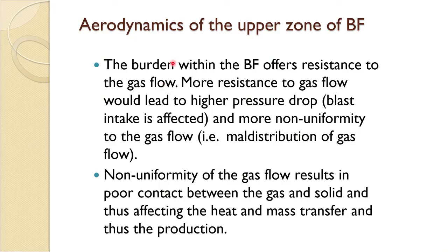It will just go without much resistance to the top, but if you put some material, naturally that material will offer resistance to the gas flow, and gas would always like to pass through the least resistance path. When you put granular material especially, it will form some voids, so gas will try to pass through the least resistance path, that is through those voids. More resistance to gas flow would lead to higher pressure drop. If those voids are smaller and smaller, the resistance is more, and it will lead to higher pressure drop.